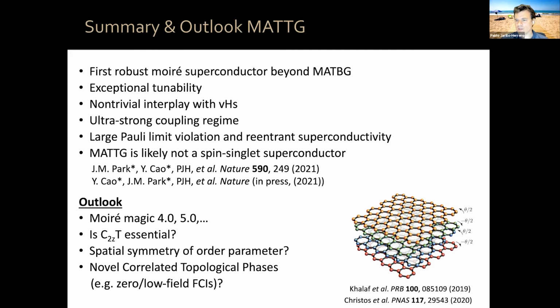Very interesting question. So for these correlated insulator states, the exact and precise nature that leads to them is still under investigation, theoretically. Now, theory is starting to converge, okay? The details vary, but it has started to converge that indeed, this correlated insulator state appears because of a spontaneous flavor polarization of some type. For example, at different filling factors, the nature of the polarization is different. The many-body ground state that flavor polarizes is different, okay? But let's say at filling factor 2 and -2, which is often the strongest correlated insulator state, there you have